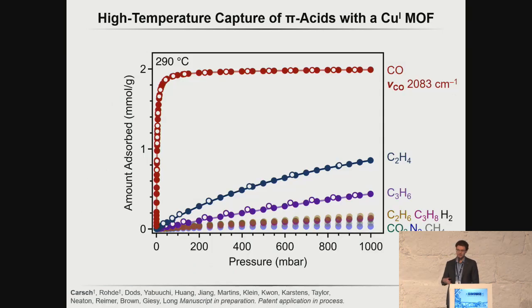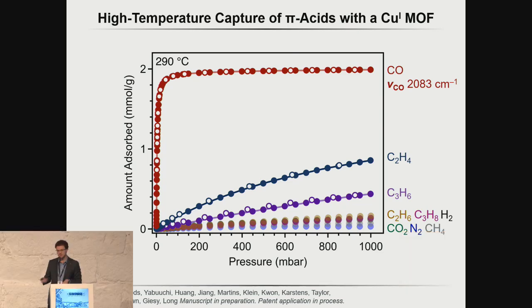Well, shown here are elevated temperature isotherms of a metal organic framework that contains copper-1 sites that has a high affinity for carbon monoxide, completely reversible at 290 degrees Celsius. The binding affinity is about 110 kilojoules per mole. We can load carbon monoxide, and then we can unload carbon monoxide. And what's exciting here is we can also undergo near-perfect selectivity of ethylene-ethane separations. This material is actually selective for ethylene over propylene because we are targeting the pi acidity, not the polarizability. And that allows us to undergo pi acid separation.